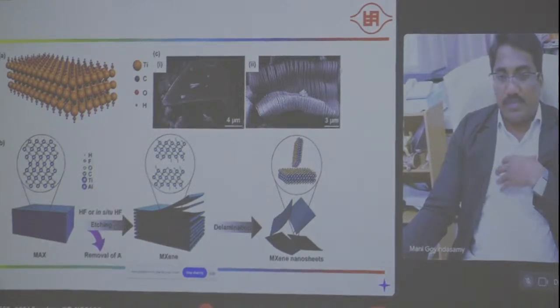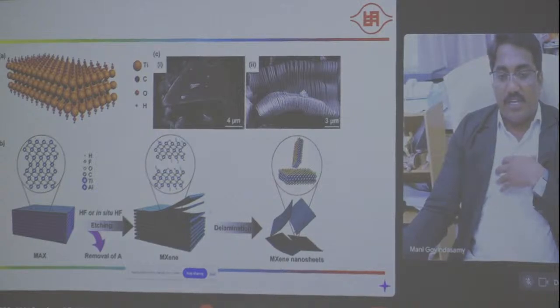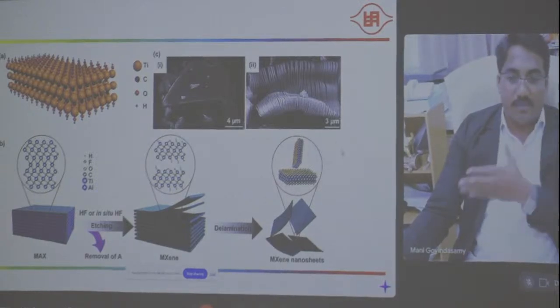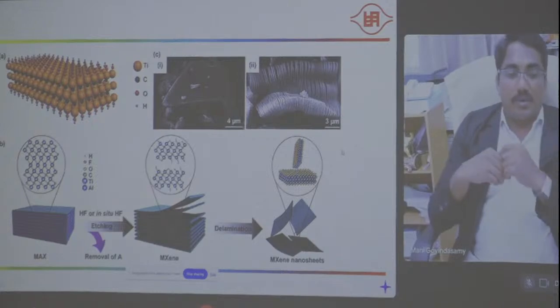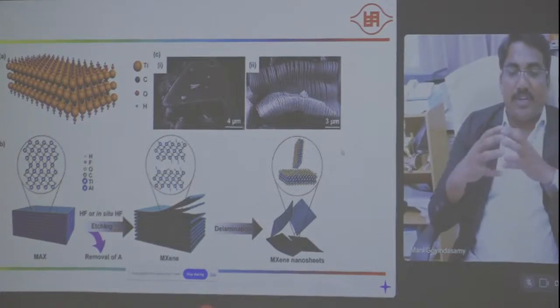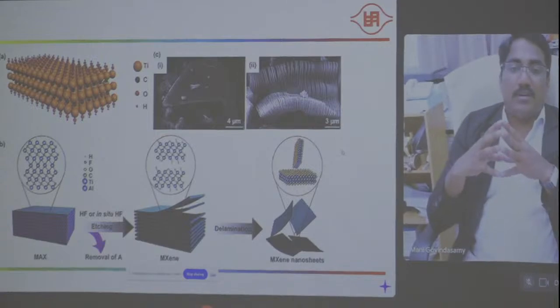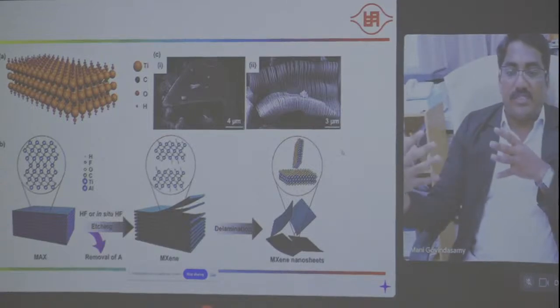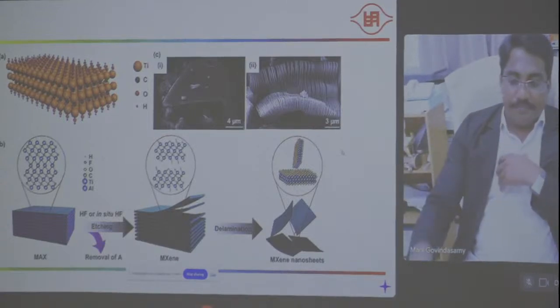After the MXene etching process, we can go for one more process, delamination. After the delamination, we can get a different structure. Maybe later we can see the procedure for how in my lab we develop different delamination processes. Then we can obtain higher interface and higher surface area.